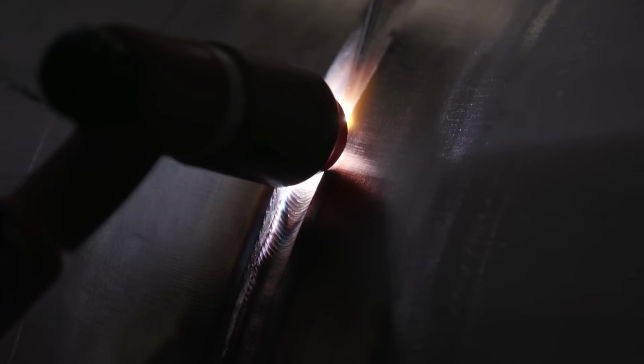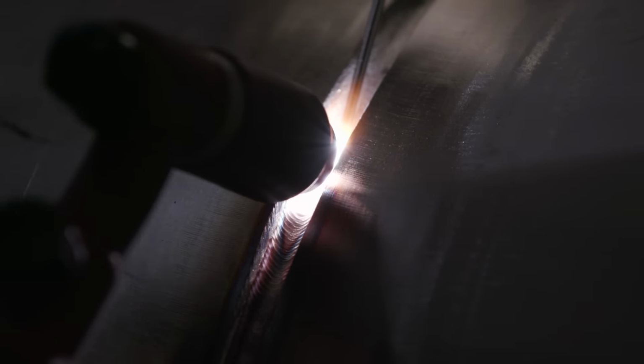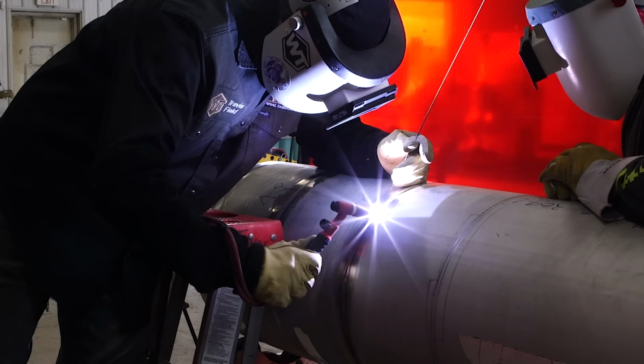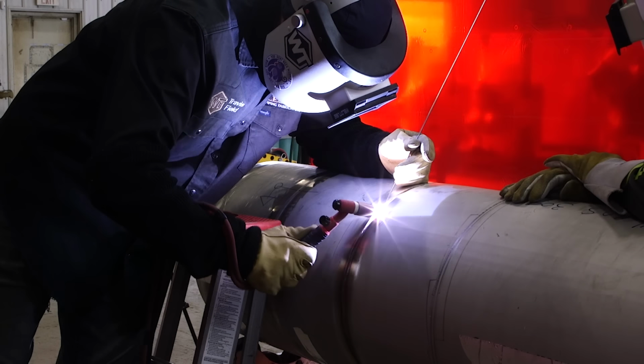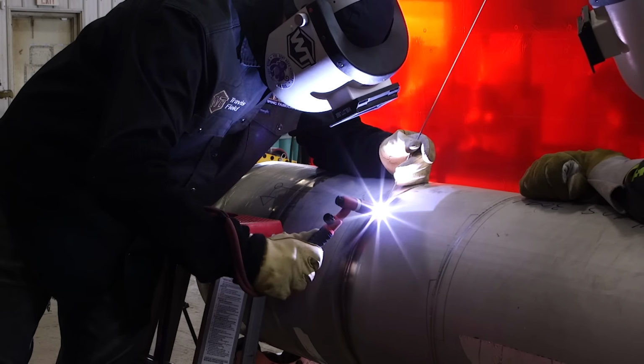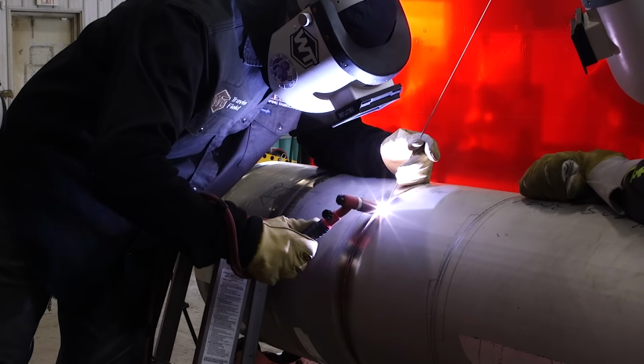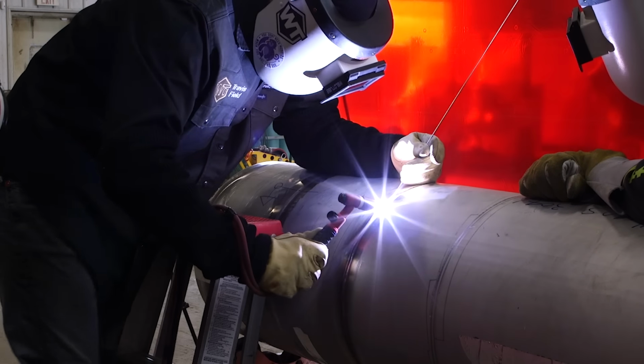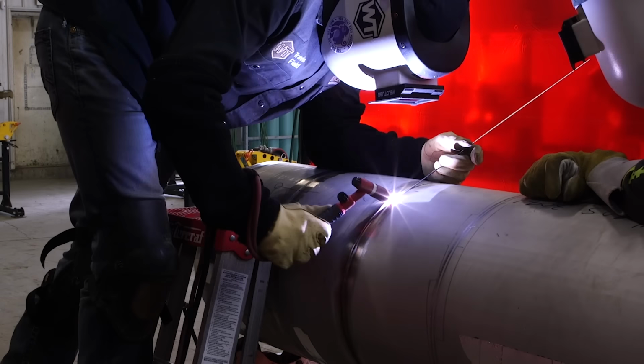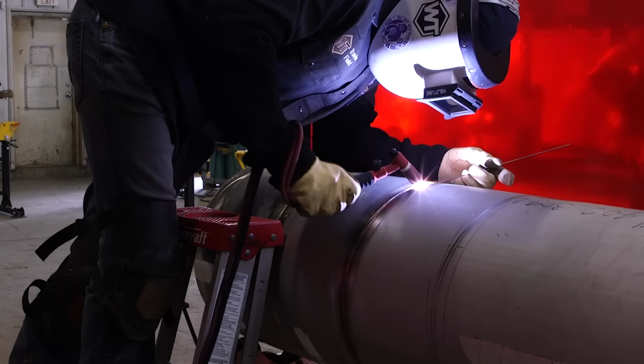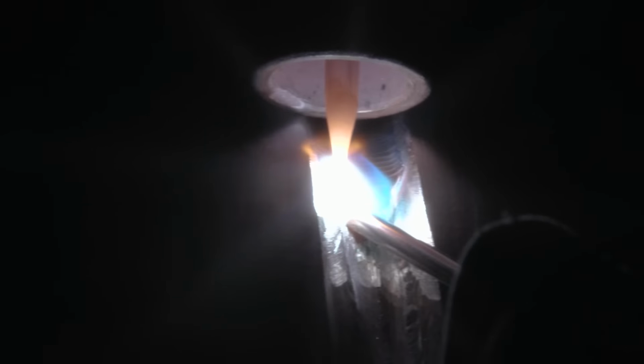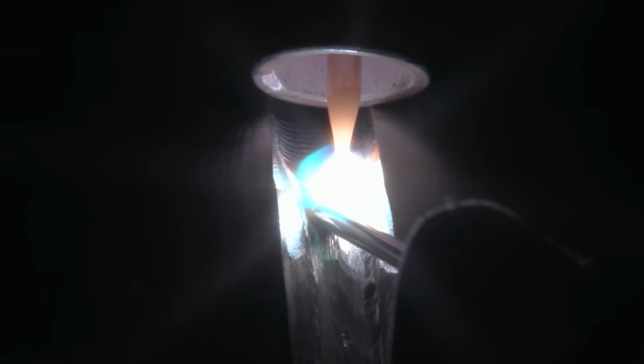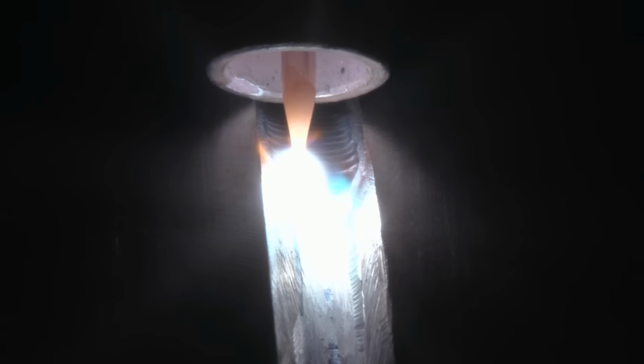And you don't have to put a lot of fill on the hot pass. Usually on the hot pass and even the first fill pass, it's pretty easy to wreck the root pass by putting too much fill. It's just essentially getting it too hot. If you get the root pass too hot, it'll get to the point where it liquefies and then it ends up rerunning portions of the root pass. It'll start melting. And it's very easy to wreck it. You get sucked back and influenced by gravity and other things.